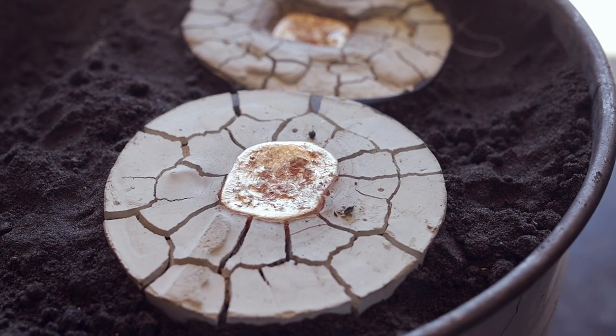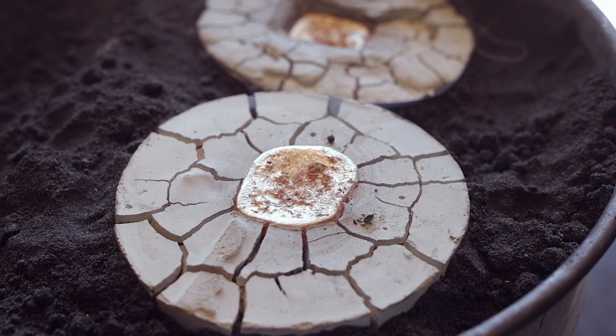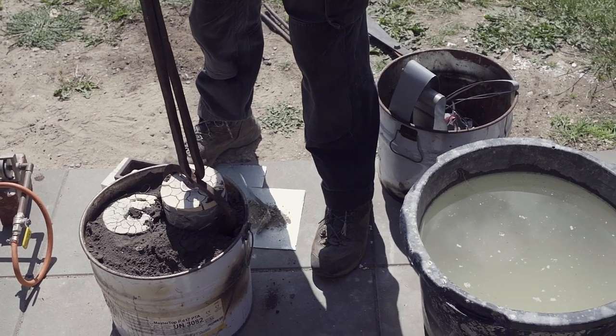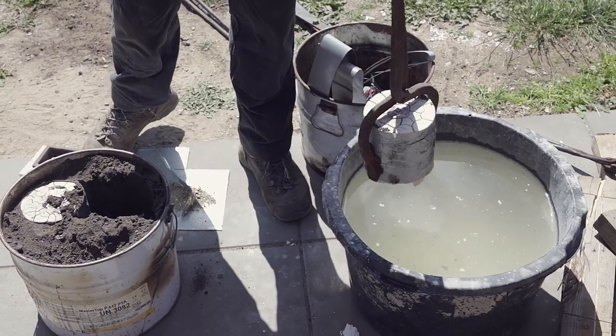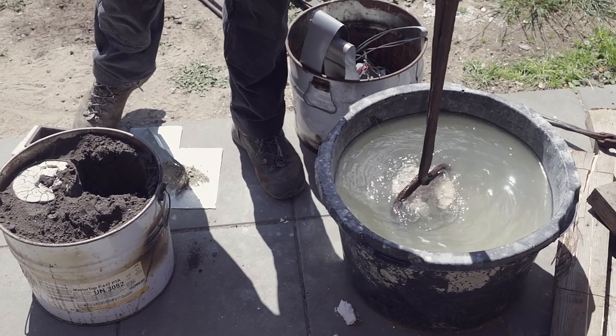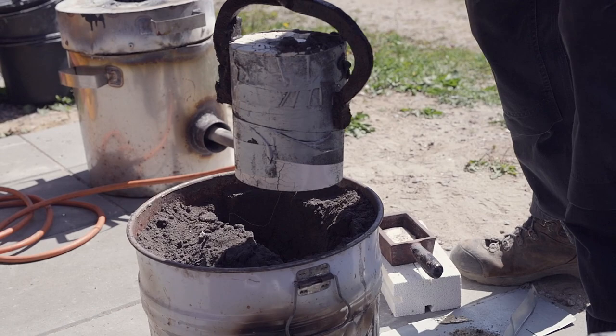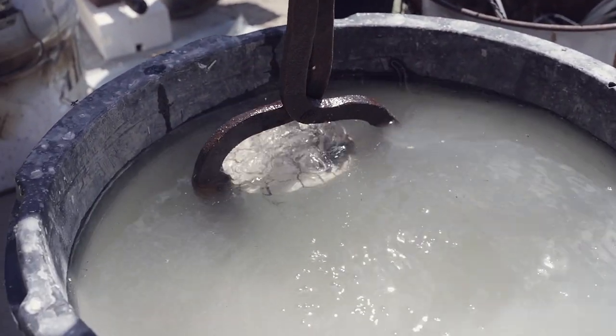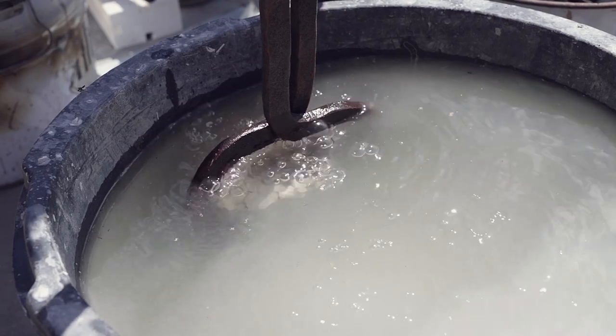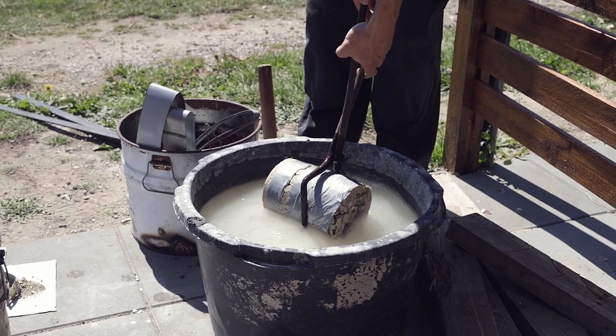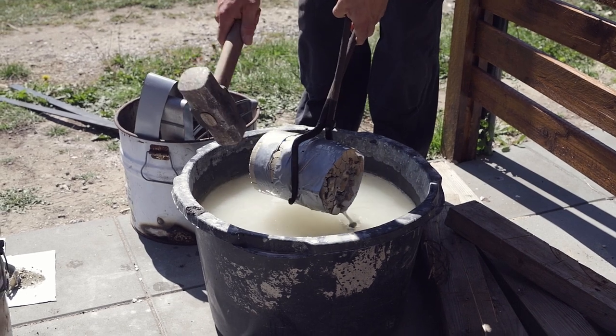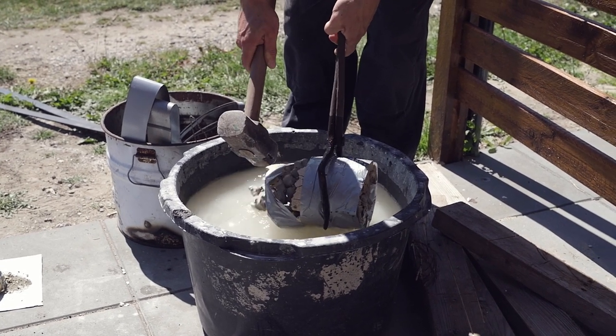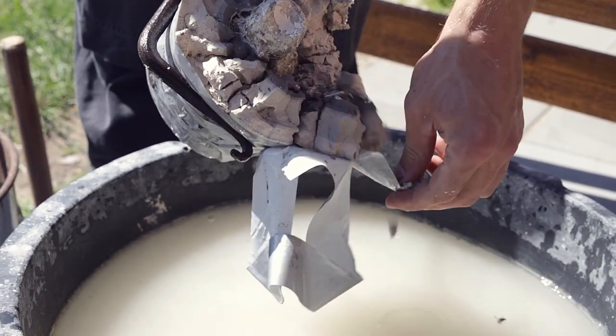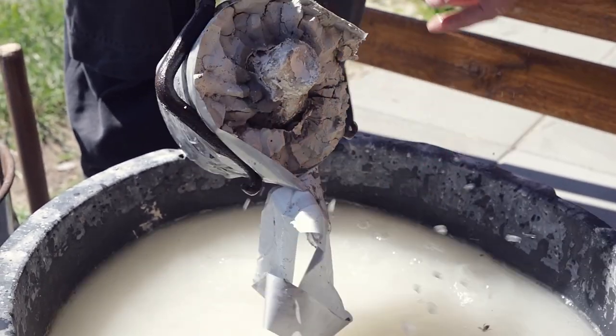Even though the cracks were not what I had hoped for, they do look quite nice. After 15 minutes of cooling, the molds can be dunked into water to dissolve the investment and further cool the metal. Now it's a moment of truth, and we'll see whether we have a bird or a disaster. Despite the severely cracked molds, we got two lovely brass birds, which are up for a good cleaning job.